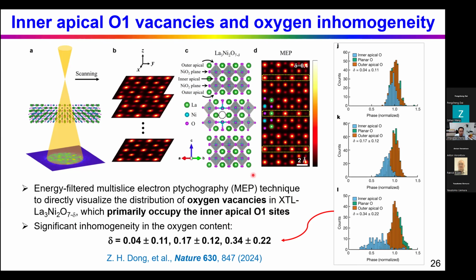There's a large oxygen content change at different regions. It changed a lot. Some regions are very close to the stoichiometry, but there are some regions that are far from the stoichiometry. So you can see this oxygen content also shows significant inhomogeneity. So both the cations and also the oxygen content show strong inhomogeneity for these single crystals.